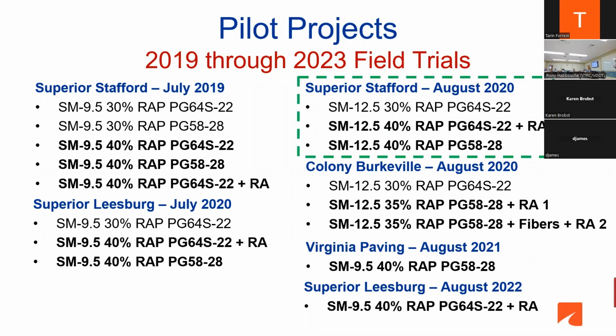So we're going to take an example and see our typical mixes compared to these engineered mixes that have a little bit more RAP. You see we're comparing 30% RAP to 40%. For us to address that high RAP that needs more stiffness, in one case we use what we call a recycling agent to soften the mix, make it more workable, and more compactable. And in the second one, instead of using a PG 64S-22, that's our typical binder grade, we bumped it down to 58-28.